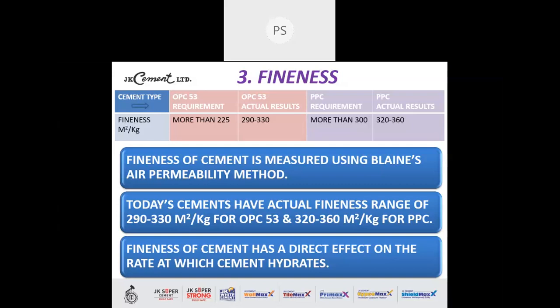If you look at it, PPC is slightly finer than OPC. More than 300 meter square per kg is the IS code requirement. We get a fineness range of 320 to 360 meter square per kg in India. Now, fineness of cement is measured using Blaine's air permeability method. Today's cements have actual fineness range of 290 to 330 meter square per kg for OPC 53 and 320 to 360 meter square per kg for PPC.